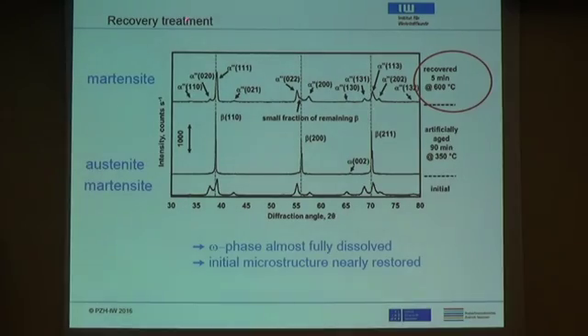Okay, so let's start with the recovery heat treatment. You have seen this data before. So initial material fully martensitic, upon aging fully austenitic. And then if you do a short 5-minute heat treatment at 600 degrees C, and then you do the X-ray, you see all the martensite peaks, they reappear. So what you do here, basically you dissolve this detrimental omega phase, more or less fully, and you restore your initial microstructure.